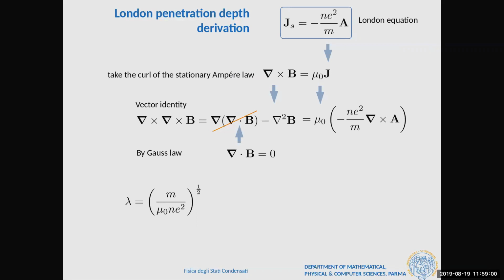The other problem is when you have a superconductor that has impurities, magnetic impurities. So in that case, it's really a problem. And this has been, we will see, the case for the pnictides. Very often in the pnictides, you haven't been able to perform the same kind of experiments that we are used to because of these nasty and ineliminable, not always, but in certain cases, ineliminable magnetic impurities. So you have to apply a field, and you're magnetizing your impurities depending on the field, so you're altering the measurement.